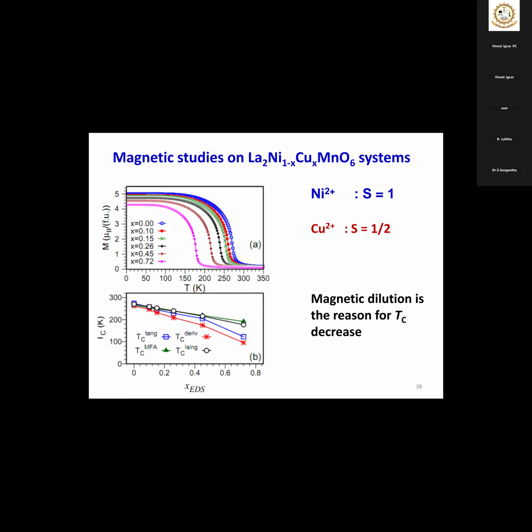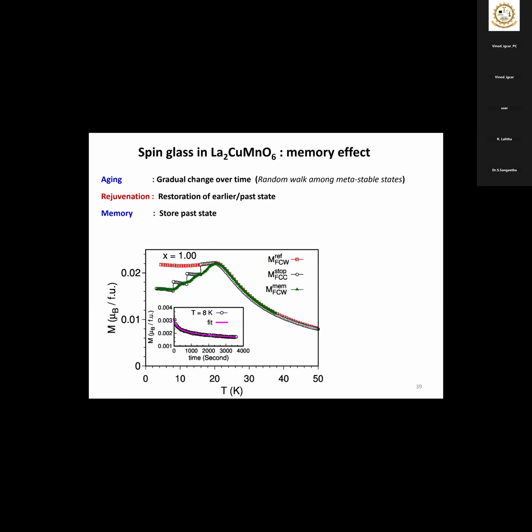So the conclusion is magnetic dilution is the reason for the TC decrease. You are diluting spin S equal to 1 with spin equal to half. So in the bond you are diluting one of the magnetic ions, and that is affecting your exchange interaction strength, resulting in the TC reduction.